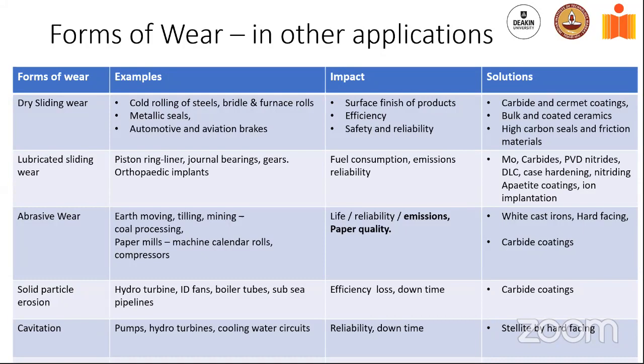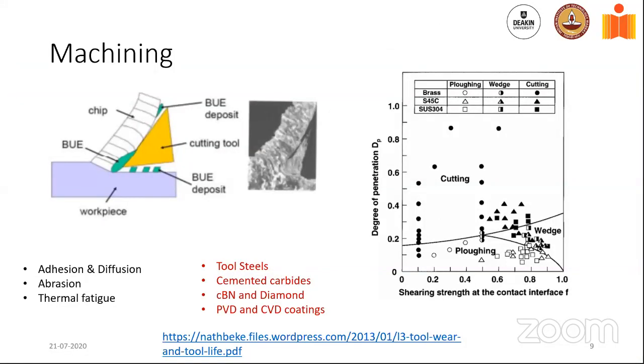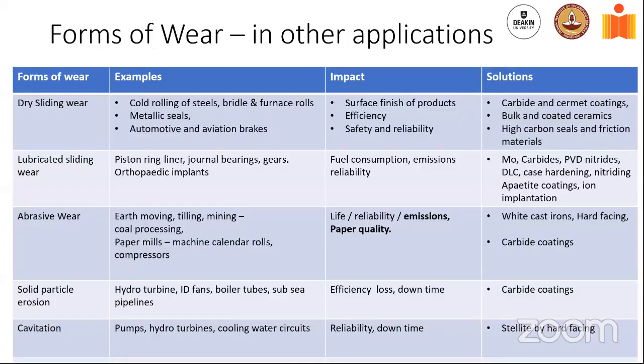The reason why it had a matte finish is because when you cold roll the steel, the wear on the rolls essentially marks the steel, and you have the steel coming out of the cold rolling mill with a matte finish because of wear. It would have scratches, it would have a matte finish, and so on and so forth.